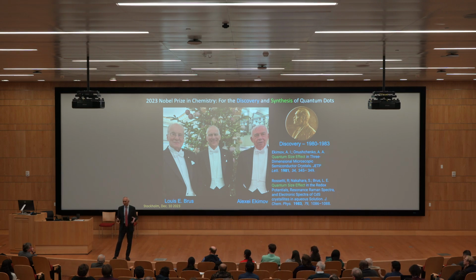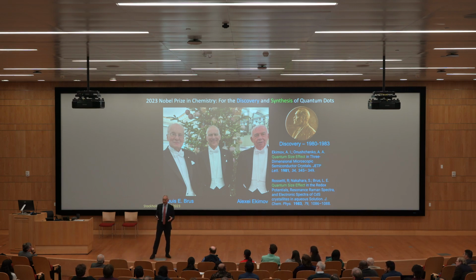That was an old concept. It was known for 40 years before I arrived at MIT. But it hadn't really been applied to nanometer-sized particles. It had been applied to much bigger particles. For instance, applied to the emulsions in photography, the silver halide emulsions in photography. So we took those things together, and as with many things, the devil is in the details. The concept is very simple: nucleation and growth, high temperature, no water. Right? You've got to actually put it together with the right chemicals. And so that's what we did, and we wrote a paper in 1993.